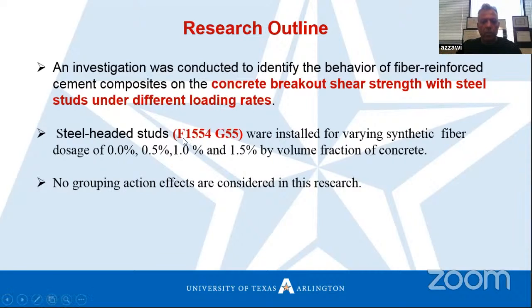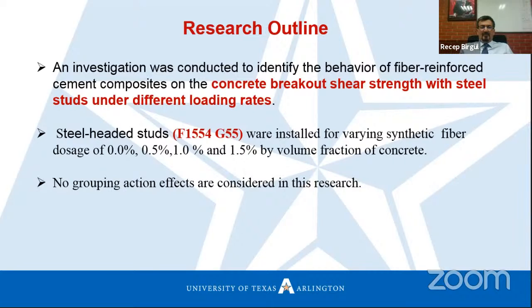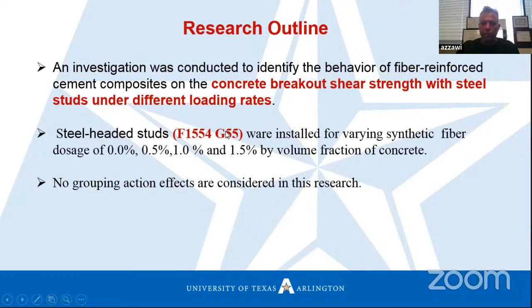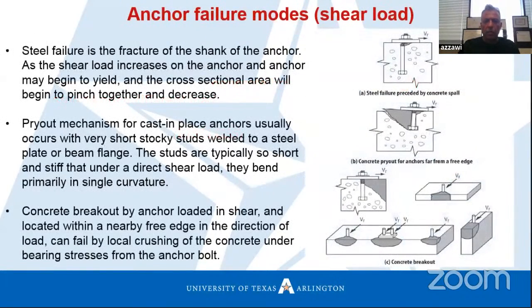We use different types of steel rods here. We are using a steel headed stud, grade 55. It's carbon steel studs, not like what we had in the previous research, which was high strength steel studs. Here I use grade 55 instead because I don't have a tensile yield problem. These studs were installed for varying synthetic fiber dosage, and no grouping action effect is considered.